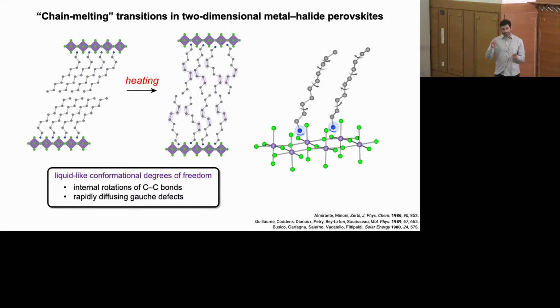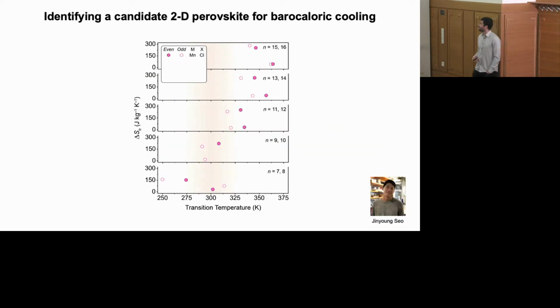In the disordered phase, things start spinning around, and you have these carbon-carbon gauche bonds that propagate through the hydrocarbon chain. These transitions are also extremely reversible, and they occur with very little thermal hysteresis because of the confined nature of these hydrocarbon molecules, so they can't really move around very much.